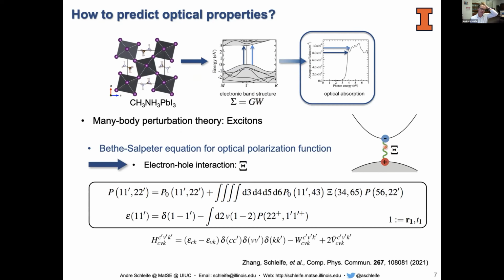People discussed this framework before. We have to look at a two-particle excitation, which means we solve this Bethe-Salpeter equation for the optical polarization function, which is given here. And then we can relate that to a dielectric function, which is what people measure, for instance, in ellipsometry. So that dielectric function here is sort of our target. The reason I'm showing you this is the following.